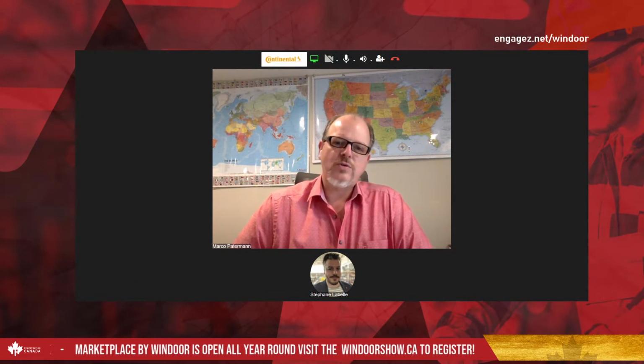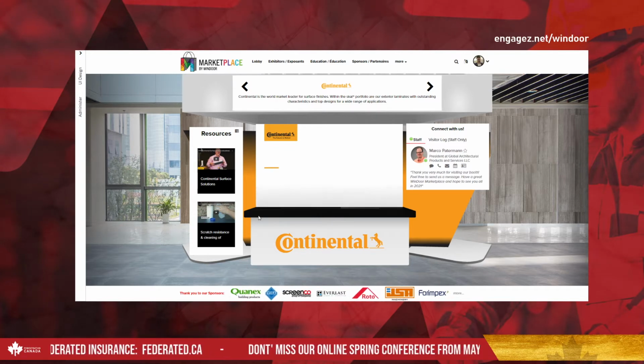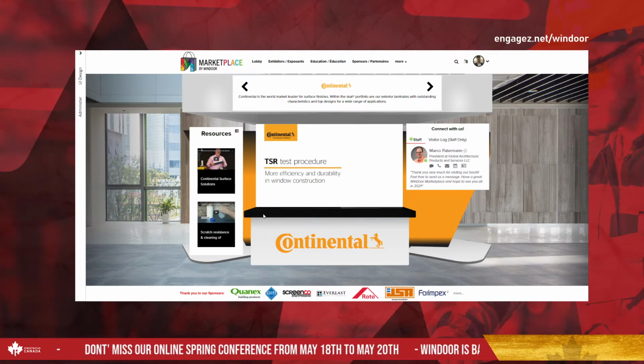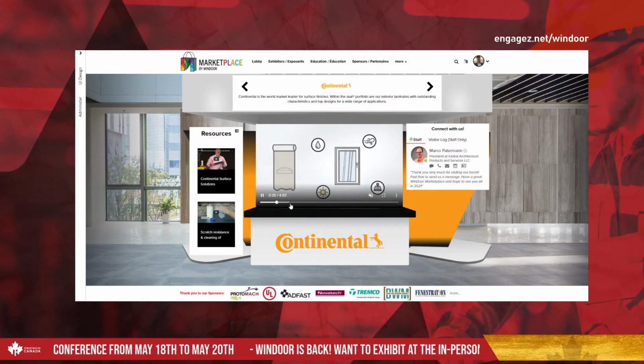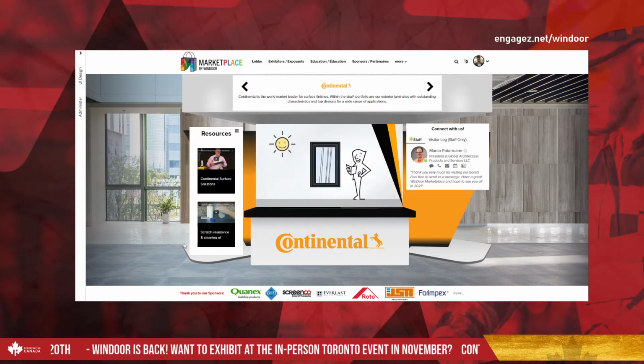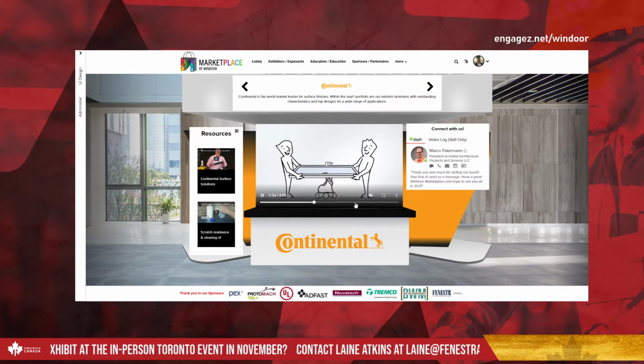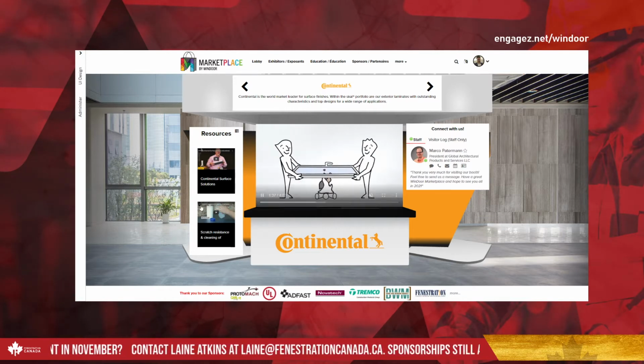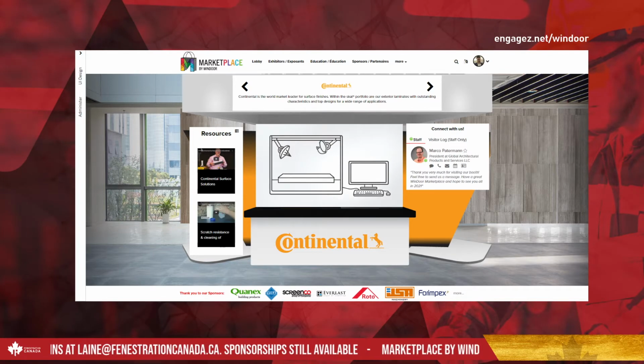So what distinguishes laminate so much? It is the quality and the longevity of the product. An average exterior laminate has a thickness of around 200 to 240 micron. That is 0.2 to 0.24 millimeter or 9 to 10 mil, which is a significantly higher thickness than any paint. It has been in the market since the 80s and has been tested in all climates worldwide. It is a multi-layer product, and it has by far the highest weather resistance of any other finish out there in the market. This has been tested by Continental, the company we represent for the laminates in North America, as well as by independent testing institutes on multiple sites worldwide.